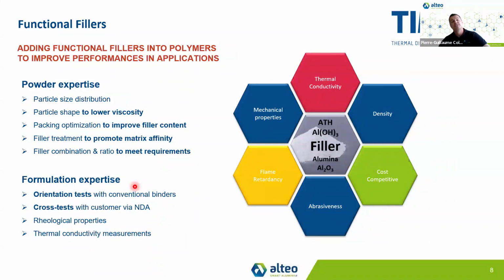So at Alteo, we do have a strong powder expertise. So we are able to work on the PSD of the powder. We can also work on the particle shape. This will bring a lower viscosity product with a lower specific surface area. We have also expertise on packing optimization to optimize and increase the filler content.